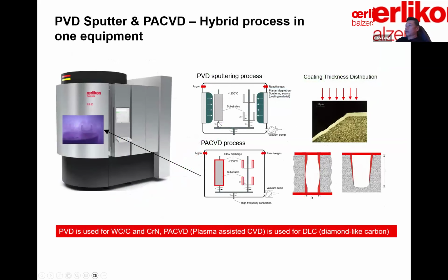So you can imagine in the coating chamber, there are these green colored coating sources, and also the sample table in the middle, which carries the substrates and creates 1x, 2x, or 3x rotations. The purpose is to have the surface to be coated evenly exposed to the coating source. So this is a line of sight process. Meaning wherever in the coating chamber can be seen by the coating source will get coated with good quality coating. Otherwise, that surface will not get coated, or will get coated with poor quality or very thin thickness. You can consider that a limitation of the coating process. I guess no technology will work for everything. This is an example of that.